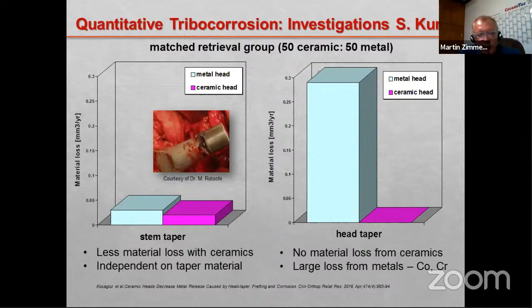Remember, if you speak about ball heads, specifically cobalt chrome ball heads, most of the metal ions released are cobalt and chrome, and that's exactly the problem you observe with metal-on-metal. Looking at the loss of material from the taper of the stem, the pink version shows slightly less loss compared to cobalt chrome. And looking at the taper of the head, on the pink side there is absolutely no loss of material coming from the ceramic ball heads.